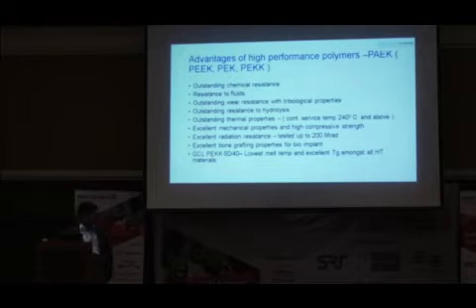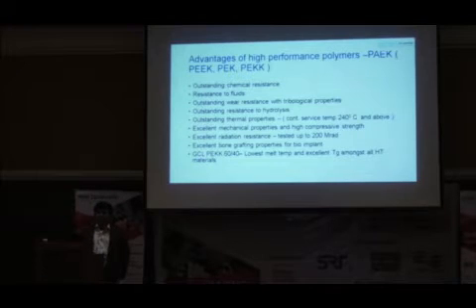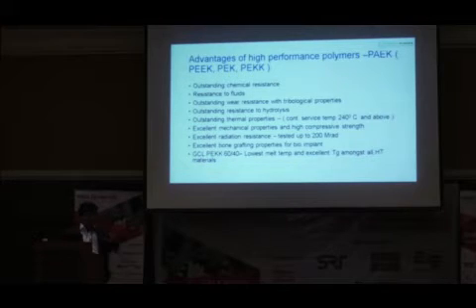So you can see PEEK. Recently Evonik has introduced PEEK medical grade 3D printing filaments. PEEK is the material, and PEKK and PEK. This material has excellent fatigue and creep resistance. So that allows them to become very stiff, and it's very lightweight compared to metal and other materials. And this material has an excellent bone grafting property. So when you put this material with the tissue, the bone and these tissues are growing very fast. So that's why it's very much compatible with the bone. And there are a lot of blends, and other new composites are at the R&D stage, where you can see a lot of blends have been created with ceramics and PEEK, and you will see a new product for biomedical implants in future.